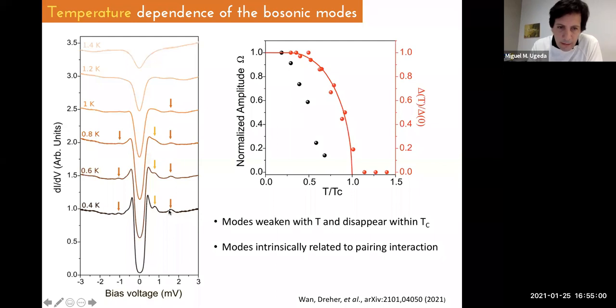So here I show you the evolution of this peak. We fitted this particular fit in order to account for the normalized amplitude starting here. This is 0.4 Kelvin, and this is the evolution of the peak. Okay, so in principle, we believe that this evolution within the critical temperature is here. So, as I said, they are totally gone within the critical temperature, or below Tc.